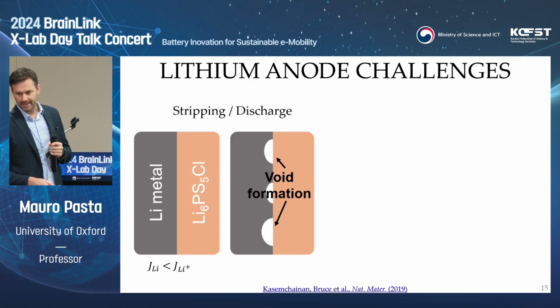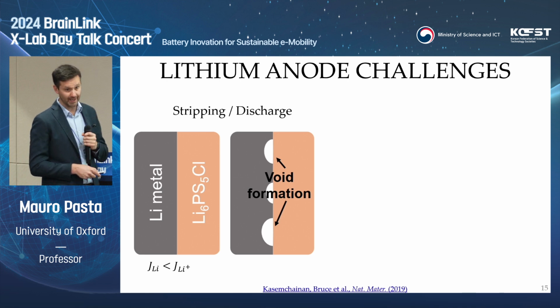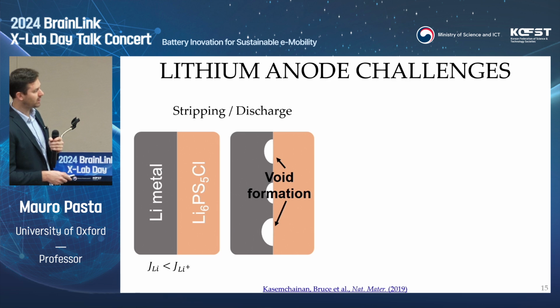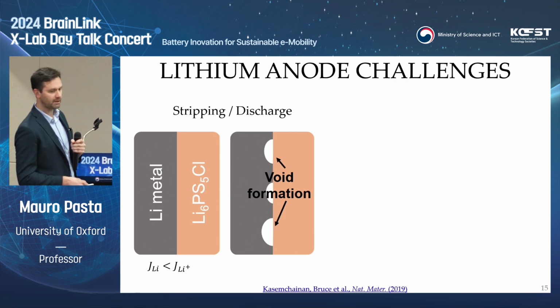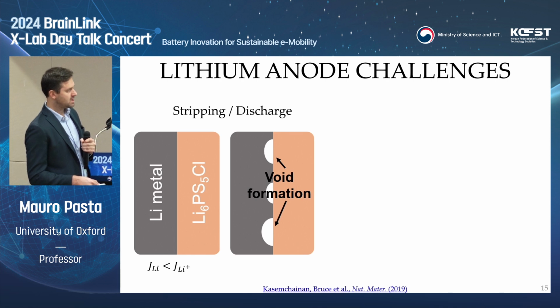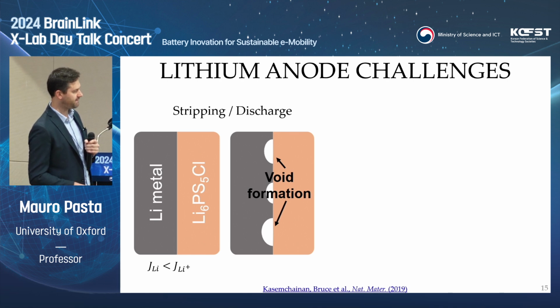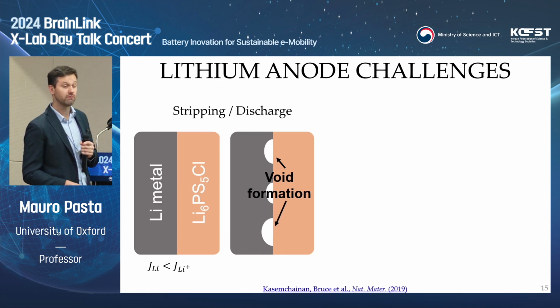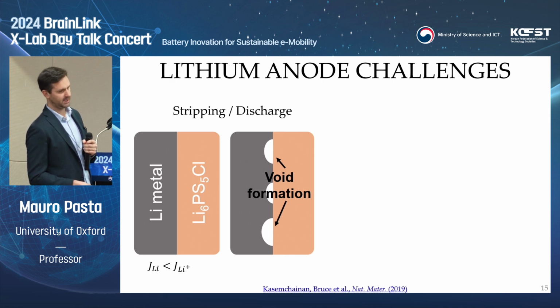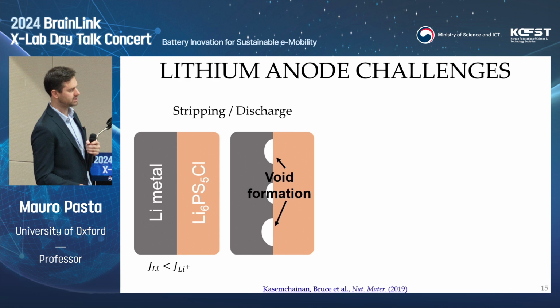Now, let's focus on the challenge of metallic lithium in this system. The whole community, and I think we contributed quite a bit through the SOLBAT project, now has a better understanding of what's going on in a solid-state battery at the lithium solid electrolyte interface. So we know that during stripping on discharge, you have the formation of voids at the interface between lithium and solid electrolytes. The origin of this void formation is found in the mismatch between the flux of lithium ions through your solid electrolyte and the flux of lithium atoms within lithium. And I'll discuss that in a second. If you have a mismatch between the 2 fluxes, you end up in principle with the formation of vacancies that can grow in size, coalesce, and form a void.